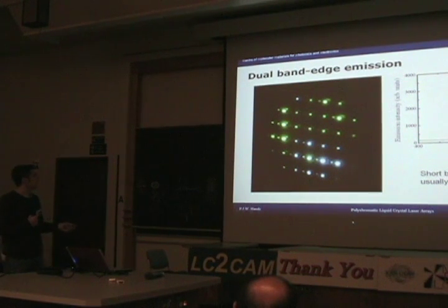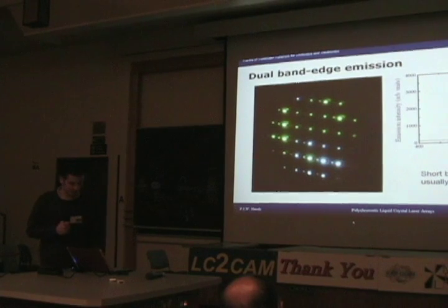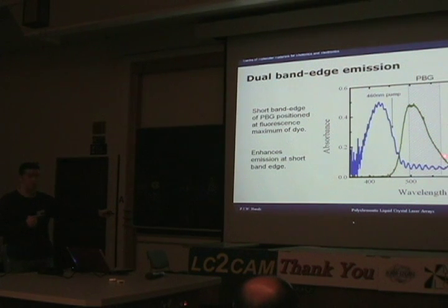So in this particular system, we happen to see two wavelengths that are separated, using a single dye system. We wanted to be sure what this was, but upon closer inspection we realised that the photonic band gap of our system, where normally the lasing would occur at the long band edge, has shifted quite a long way down the green line, which is the emission spectrum of the dye. We're actually at a much lower emission probability.